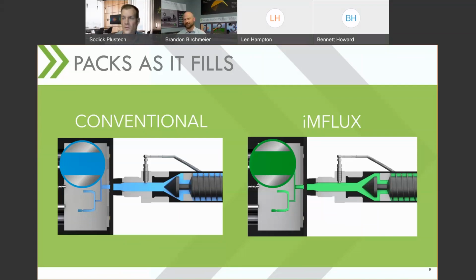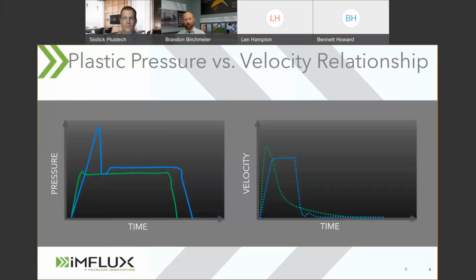In family molds, I should touch on family molds. Family molds are completely fine with the iMFLUX process. We've demonstrated those time and time again because cavity balance isn't so critical to our process. Think about why cavity balance is so important in a conventional molding process. I'm going to go back to my graph here. It's because of that pressure rising at constant velocity. Let's say I have an 8-cavity mold. That first cavity to fill is going to see more pressure than the last cavity to fill, because the pressure continues to climb at a constant velocity. So those cavities are different from one another because they fill differently.